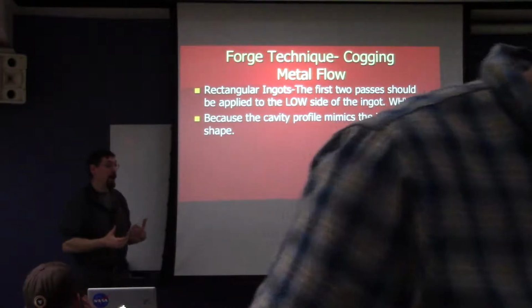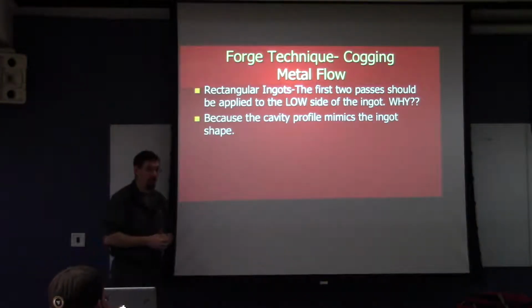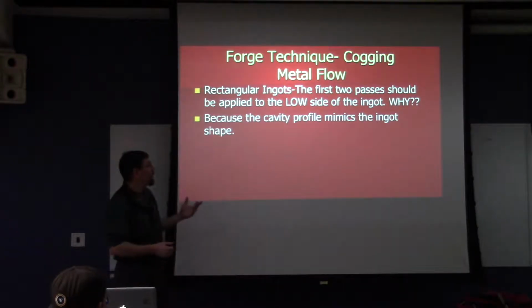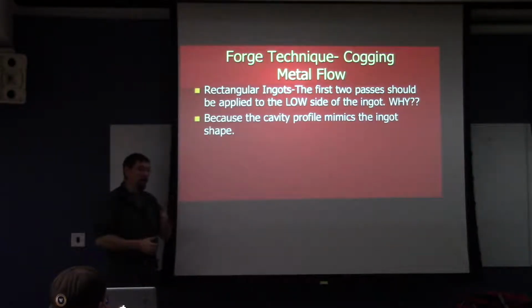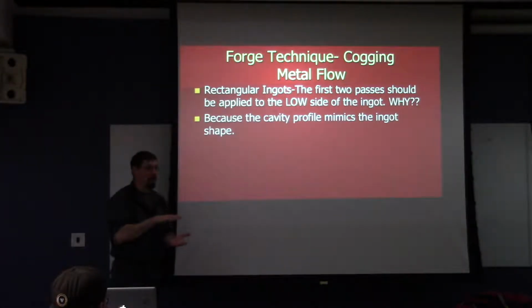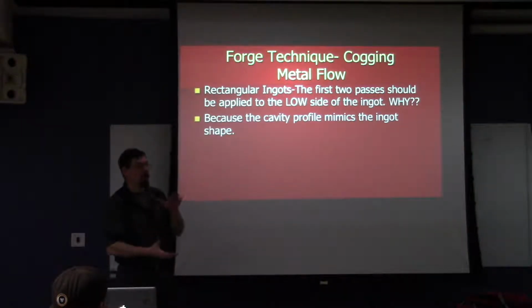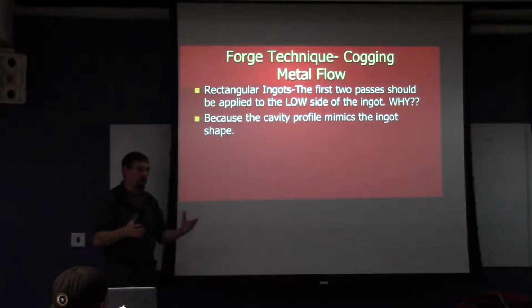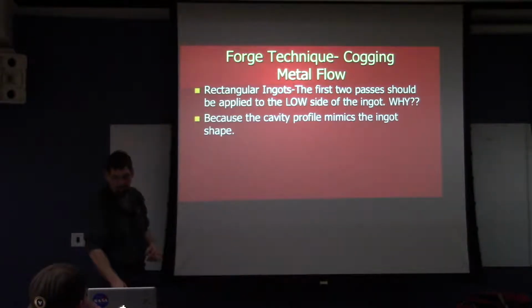Again, this comes back to equipment capacity, but if we're able to do it, making our first pass on the low side of the ingot is going to be preferred, because it's going to help close that shrinkage cavity more rapidly than starting on the high side of the ingot. Sometimes we're not able to do that due to equipment limitations. And again, that's okay as long as we understand that and adjust our process accordingly so that we get the effective reduction at the right place in the process.